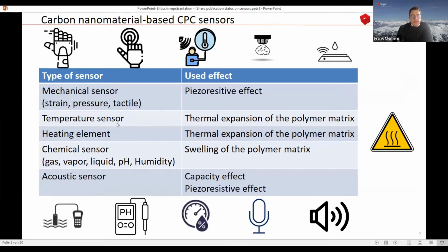So we can also make a heating element by applying a high voltage and so allow a certain current to pass through the material. And then we can also use the thermal expansion of the polymer matrix to adjust the temperature which we want to achieve by applying a certain voltage and a certain current.